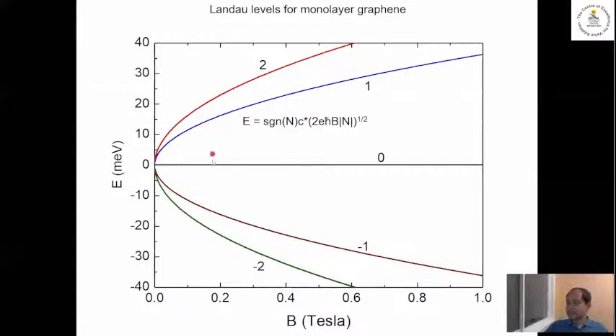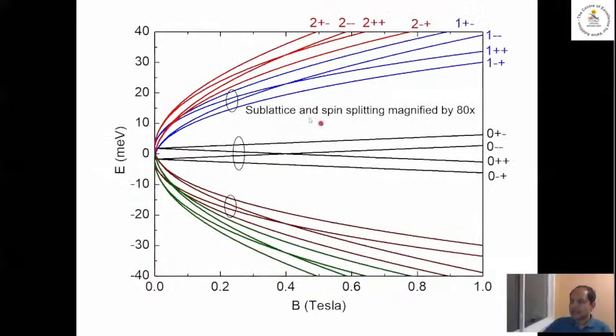Now the thing is, each of these levels is 4-fold degenerate. That means there are actually 4 lines on top of each other: 2 for spin degeneracy and then 2 for sublattice degeneracy. Let's put that in, but now we're going to magnify the splitting by a factor of 80 so we can see it. Otherwise, splittings are going to be tiny and it won't show up on our pictures here, right? So each of those levels was 4-fold degenerate. We said we're going to lift the degeneracies. Then we get 4 distinct levels.